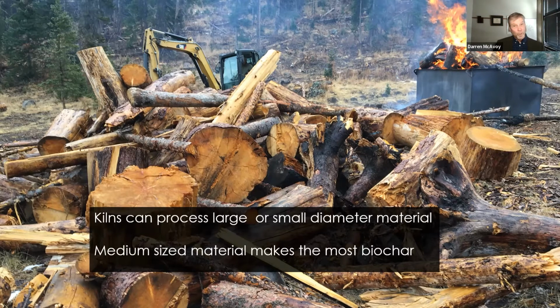But if you're more interested in the biochar production, you could slide that scale towards that side by quenching more frequently and trying to preserve that char. We can make biochar, and we did, just fine from this large diameter material. But if biochar production is the most important thing, we find that more consistent piece sizes, perhaps 7 to 10-inch diameters, is ideal for biochar production.